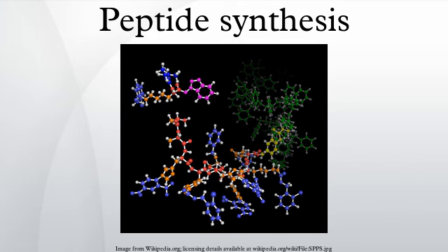PEG hybrid polystyrene resin. An example of this type of resin is the TentaGel resin. The base resin is polystyrene onto which are attached long chains of polyethylene glycol. Synthesis is carried out on the distal end of the PEG spacer, making it suited for long and difficult peptides. In addition, it is also attractive for the synthesis of combinatorial peptide libraries and on-resin screening experiments. It does not expand much during synthesis, making it a preferred resin for robotic peptide synthesis.